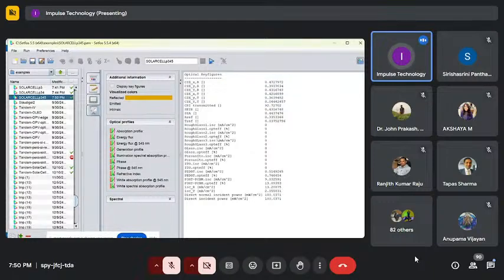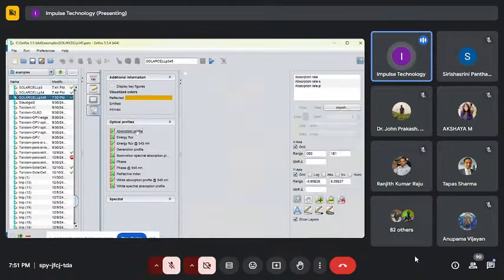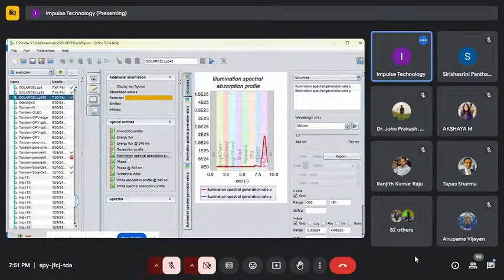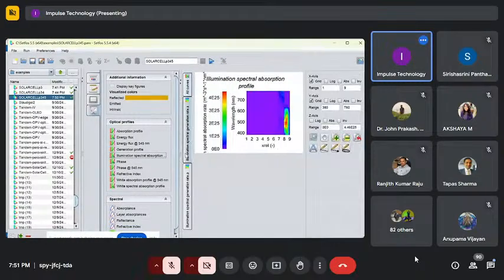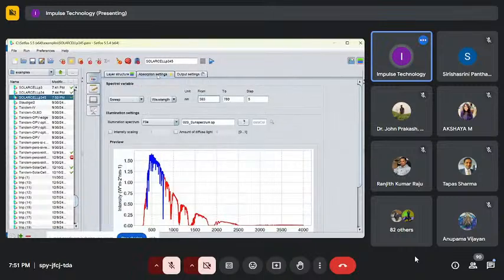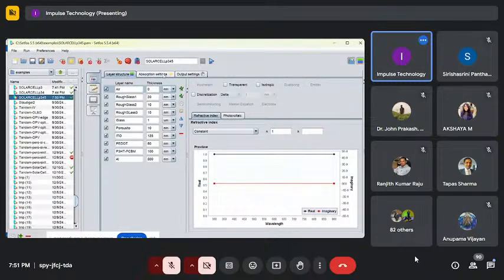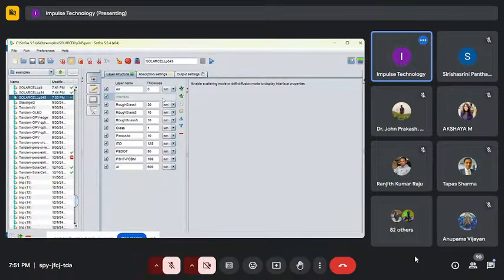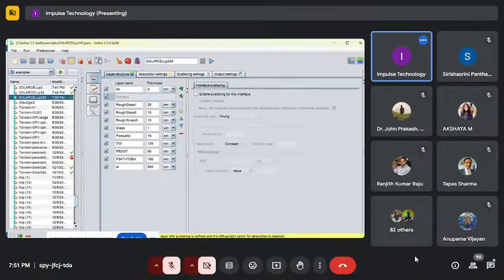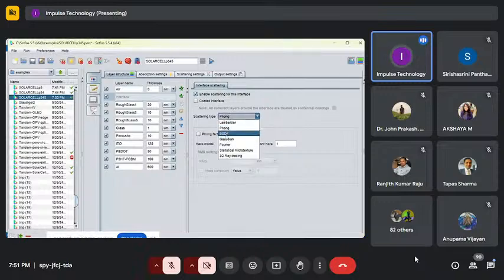Here, with the rough glass interfaces, you can see the effect. You can see the current for the P3HT:PCBM is increased. So rough interfaces decrease the reflectance, and you can see the profiles here: generation profiles, illumination spectrum files, wavelength on the x-axis. I am generally using the absorption and scattering modules here. Now if you want interfaces, you can add interfaces here, and you need to activate spectrums, and you can also give them here. And if you want to run your simulations, you can easily run them here.